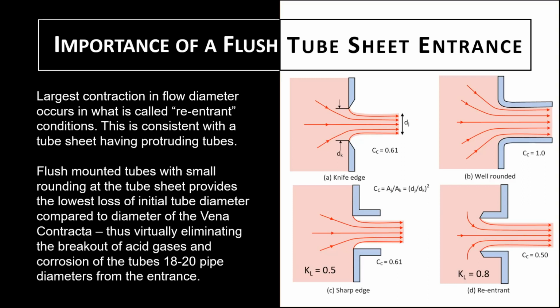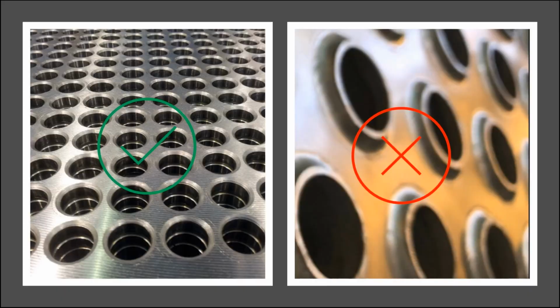Now the combination of the higher reduced area and the higher K value can cause excessive velocities, which means a high velocity pressure, which also means a low static pressure. And this static pressure drop can be severe enough that we can flash acid gas out of the solution as it enters the tubes. And we tend to see the corrosion manifesting itself around 18 to 20 pipe diameters from the entrance of the tube. So that means we want to have the tube sheet that looks like the picture on the left, with slightly rounded entrance conditions as opposed to the protruding tubes in the tube sheet to the right if we want to reduce corrosion within the system.